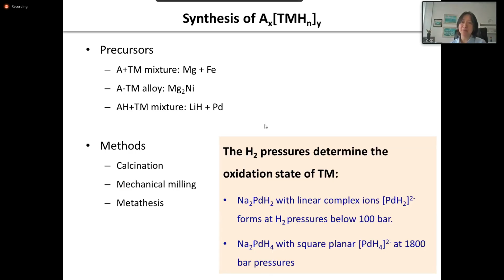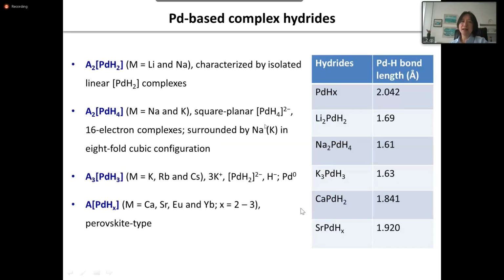For example, for sodium palladium hydride, if you have a synthesis condition around 300 degrees Celsius and a pressure of 100 bar, you probably have Na2PdH2. But if you apply extremely high pressure, like 1,800 bar, you probably have Na2PdH4 there. So hydrogen pressure is critical in determining the oxidation state of the transition metal. Particularly, I just list a few palladium-based complex hydrides here. You can see that palladium can bind with 2 hydrogen, 4, 3, or between 2 and 3. So this combination gives you different structures and different valence states of palladium.